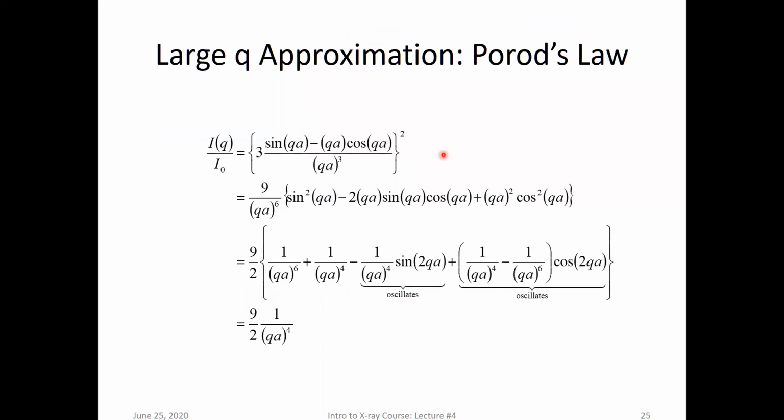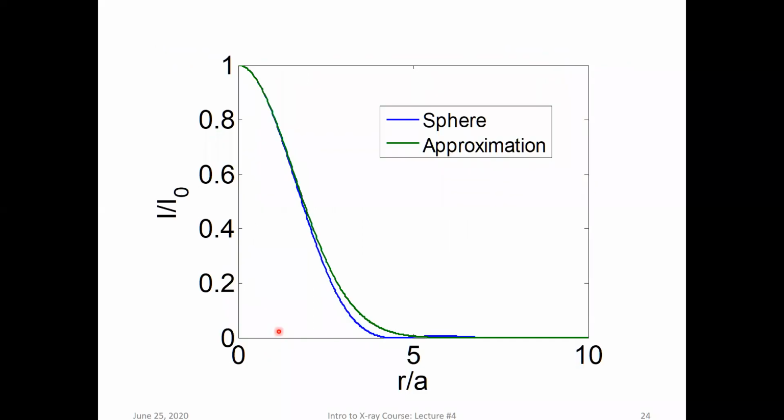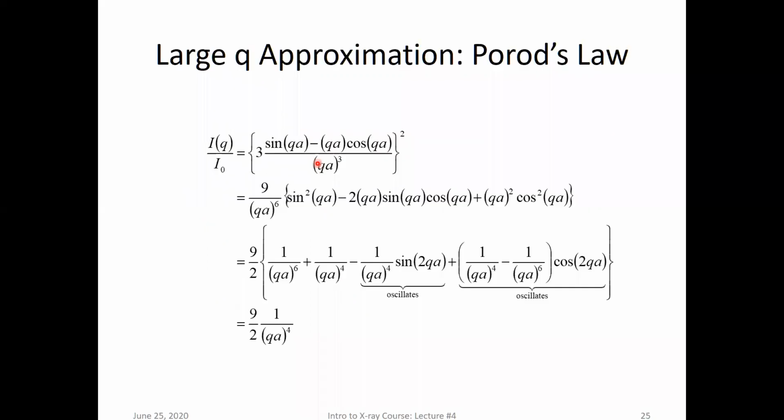And so with my small angle scattering, I can get the size of my object in the two different approximations, in the far field and in the near field. And that's the basis of small angle X-ray scattering, then used for all kinds of studies of protein folding and unfolding. It's commonly used now. So the biological small angle scattering community is huge at this point. Also, a lot of work in the polymer community, getting radius of gyration and so on.